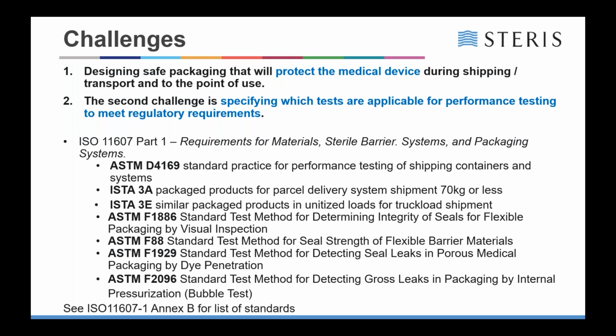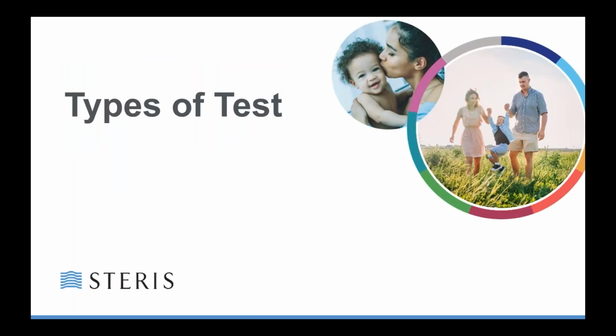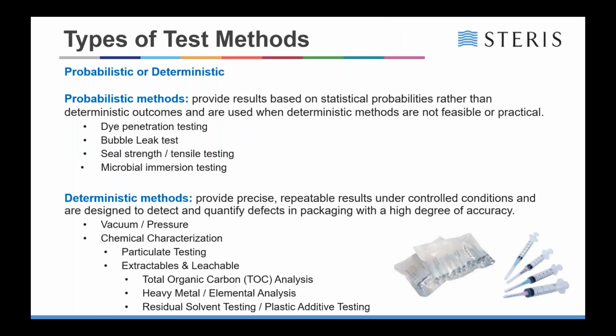Say, for example, if you're to look at distribution testing, you'd use the likes of ASTM D4169 or ISTA 3A or 3E. If you're looking at the integrity of your pouch, you'd start with a visual inspection to ASTM F1886, and then do the likes of a dye penetration to F1929 or F3039, and also then F2096 is your bubble leak testing, followed by either a burst test or a peel strength or seal strength test to the likes of ASTM F88.